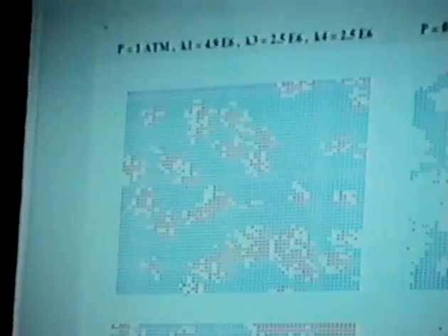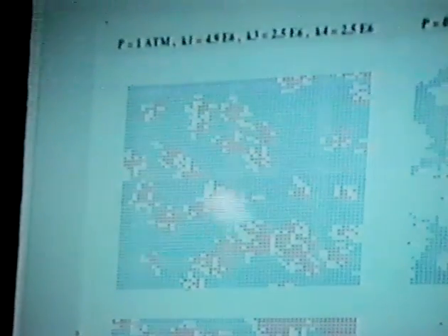This is another simulation of a surface that is initially covered by oxygen, and these are two conditions: first, atmospheric pressure, and a lower pressure here. What we're doing is putting CO in the gas phase. We start with the oxygen covered surface and a little bit of CO, and you see again the formation of these aggregates and the formation of larger domains here. These are steady state conditions after about 10,000 iterations probably.